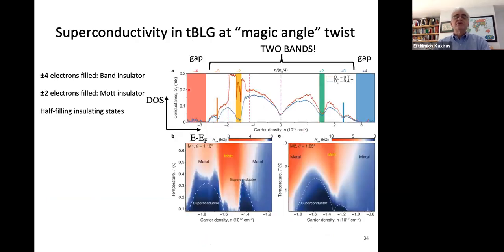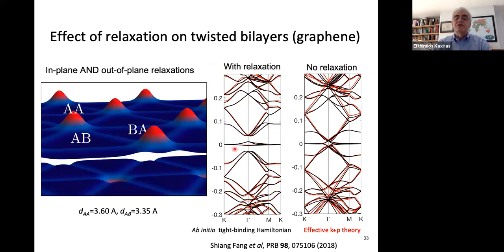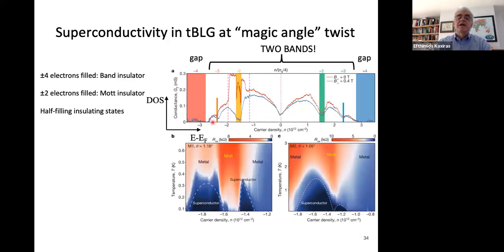So going back to the superconductivity observations in twisted bilayer graphene at the magic angle, you see that what I just showed you actually creates a big puzzle, because I showed you a moment ago these two bands, which are separated by band gaps from the rest. They are pretty flat, and that gives the large density of states. And here's essentially, on the vertical axis, the density of states as a function of energy relative to the Fermi level. The Fermi level is at zero. And you see that you have this gap here and another gap on the other end.